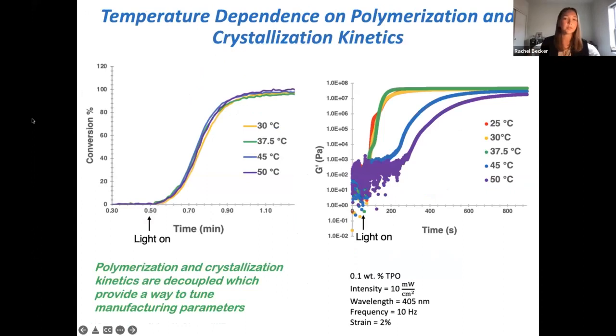So now looking at the temperature dependence of the polymerization and crystallization processes, on the left, I have FTIR data of 4 temperature samples from 30 degrees up to 50 degrees, and we have conversion percentage plotted versus time. And as you can see, when the light turns on, all 4 of these samples polymerize pretty uniformly at the same rate. So we can conclude that polymerization is going to be independent of the temperature.